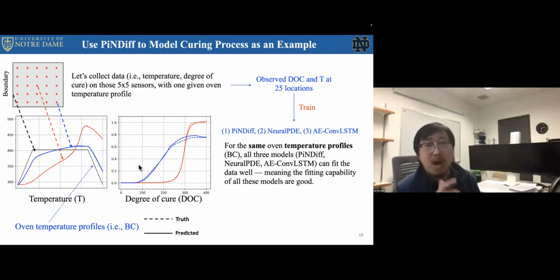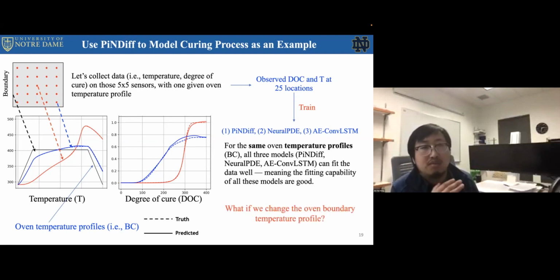For all 3 models, if you test on the same oven temperature profile, all 3 models can fit the data very well. That means the data fitting capability of those models is pretty good, right? But what we really care about is what if we change this oven temperature profile, not just going up, remaining constant and going up, but maybe a different temperature profile. Can these models still generalize to those unseen boundary temperature profiles?